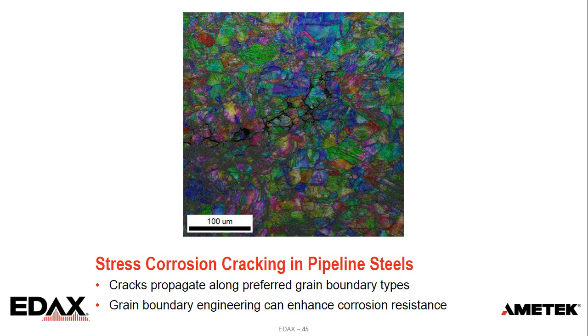And this can be important for something like stress corrosion cracking. This is in a pipeline steel. This is just an example of a crack going through a piece of this steel. The cracks tend to propagate along specific grain boundary types. They generally try to avoid going through a twin boundary. And so there's work called grain boundary engineering, where materials are subjected to different deformation and heat treating cycles to increase the number of twin boundaries to help enhance the corrosion resistance.